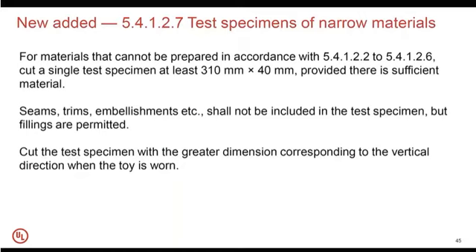Also, there is the chapter 5.4.1.2.7, which is related to the test specimens of narrow materials. So for materials that cannot be prepared according to the previously described points, cut a single test specimen at least 310 millimeter per 40 millimeter, provided there is sufficient material. So seams, trims, embellishment shall not be included in these specimens, but filling is permitted. And also in the preparation of the specimens, there is the need to cut it with the greater dimension corresponding to the vertical direction when the toy is worn.